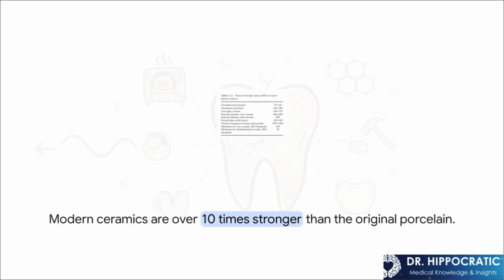Adding zirconia to that sintered alumina core gets us to 800 MPa. And the current king of the hill, a wild material called yttrium tetragonal zirconia polycrystals, can reach up to 1200 MPa. That is more than 10 times stronger than the porcelain we started with. It's just an amazing story of scientific progress.